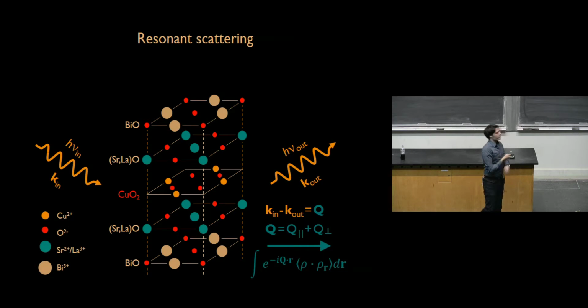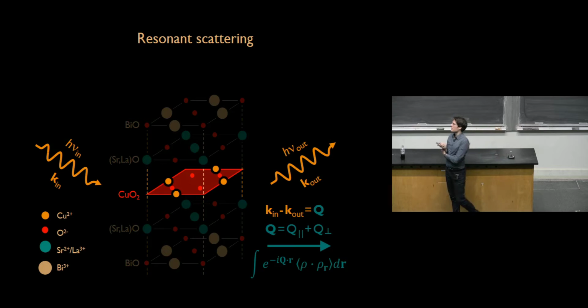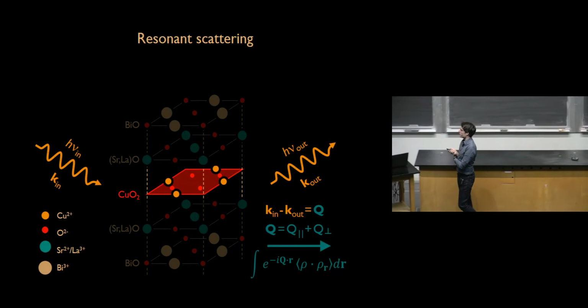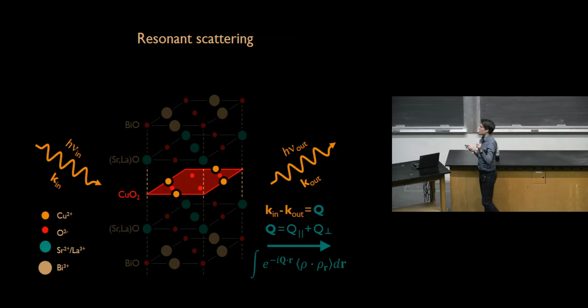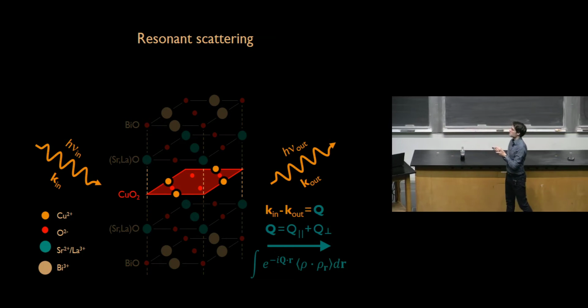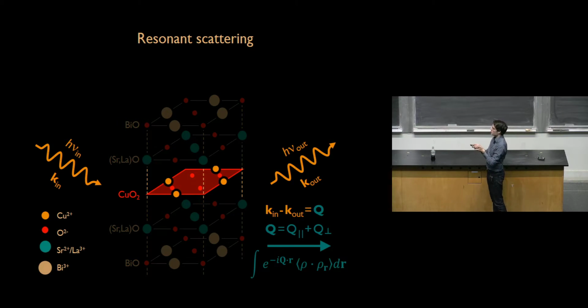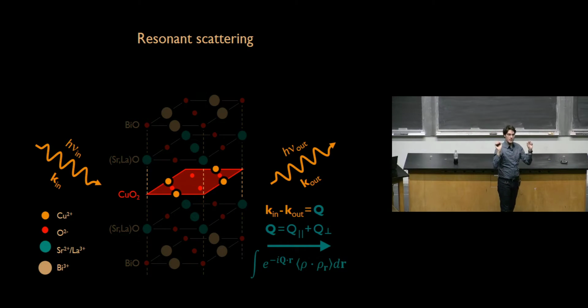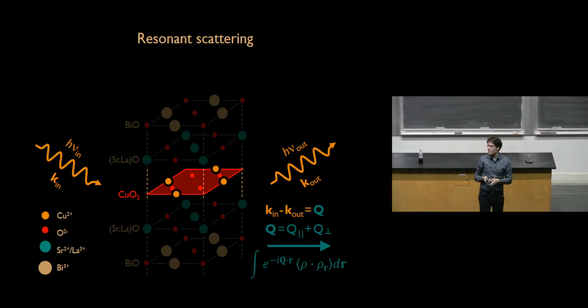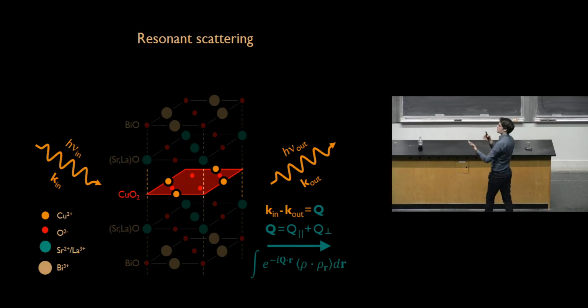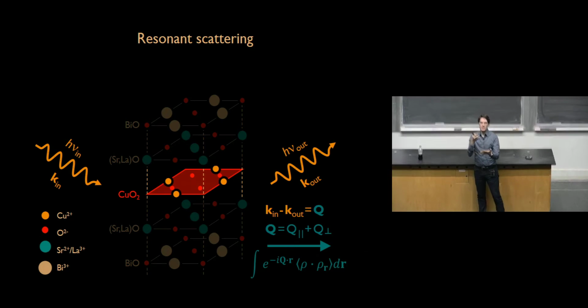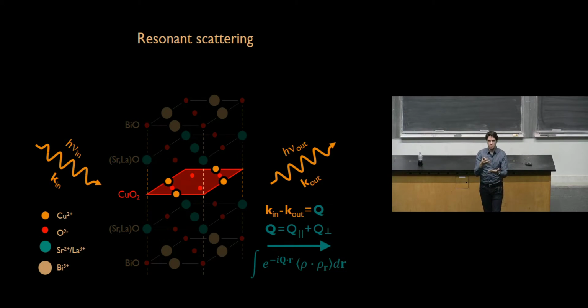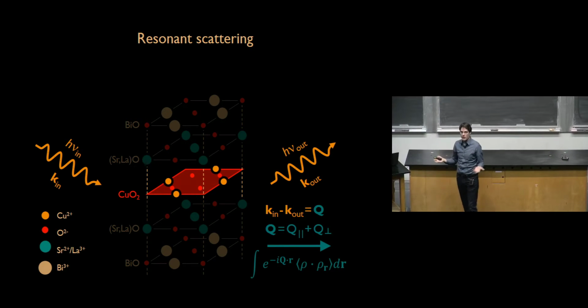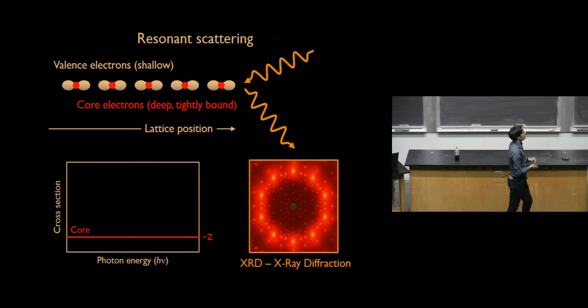And so with resonance scattering, which is what I'm going to talk about today, we can do essentially site-selective crystallography. And not only that, so not only can we focus on certain atomic species in our material, and specifically I'm going to talk about cuprates. So we're going to focus on the copper-oxygen plane. So we're going to work at the resonance of copper atoms. But we can also enhance the contrast from just the valence or conduction electrons in my material, as opposed to regular crystallography where the core electrons will dominate. And we're not interested in the core electrons. We're interested in the valence electrons.